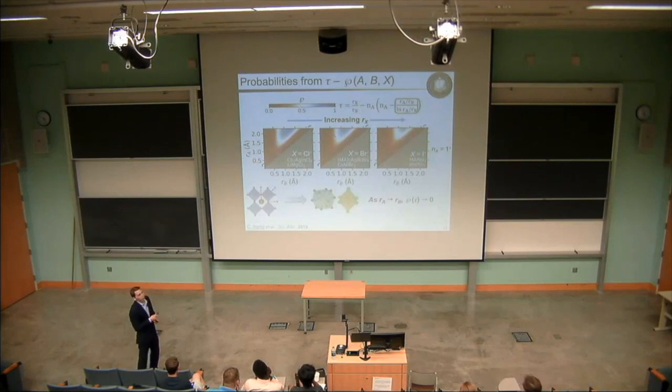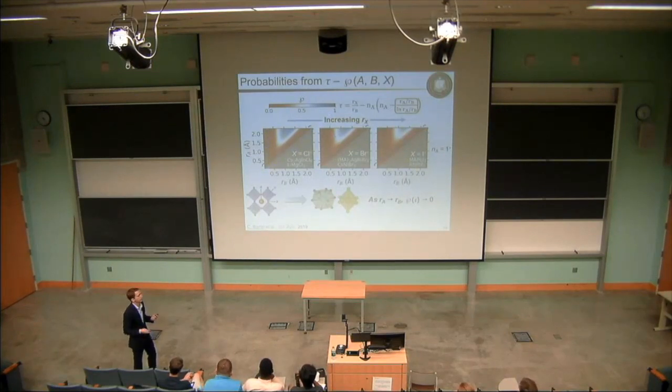Similarly, we can look at this more complex term. So this is the cation radii ratio divided by the log of itself. And at first this might look a bit suspicious or strange that the learning algorithm would pick this kind of term. But the way it manifests in the probability map is that when these two radii ratios are equal to one another, or when the ratio equals 1, or the two cations have similar size, then the probability of forming perovskite goes to 0. And that's evident by this dark red region right around the y equals x line.